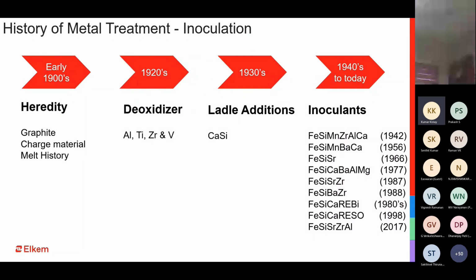Until the time before sulfur and oxygen was added to the inoculants, they were supposed to react with the sulfur and the oxygen present in the base metal and then give the inoculating effect. But then one of the scientists came up with sulfur and oxygen coated inoculants. Quite proud to say he was from Elkem, who invented this sulfur and oxygen coated rare earth based inoculant, which was bringing its own sulfur, its own oxygen into the system, and thereby the dependence on the nucleating potential of the base iron came a bit less. Even today it is one of the most potent inoculants for ductile iron.